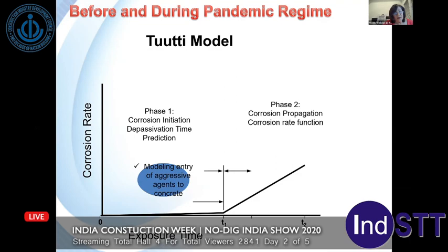We process all the data statistically. We use first a mathematical model, multiple linear regression, trying to find the effect of meteorochemical, but also electrochemical parameters on the corrosion rate. From this, we made a linear multiple regression model. We found, taking into consideration the water cement ratio, the exposure phase, the rebar cover thickness, the geographic location, and also without restriction, that the most important parameters were the exposure time, the capillary absorption, the alkaline reserve, the relative humidity, precipitation, and temperature. And those are some of the models that we found.